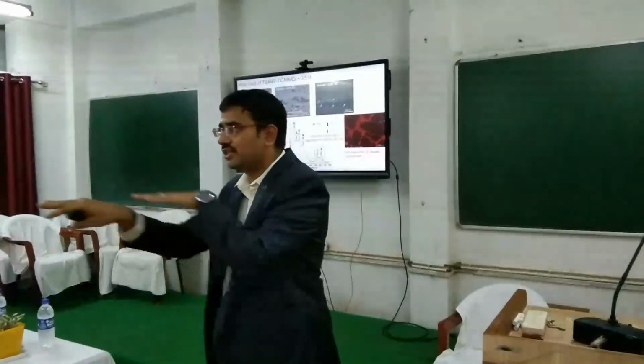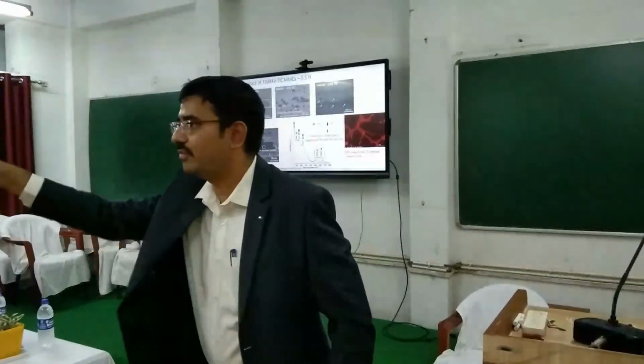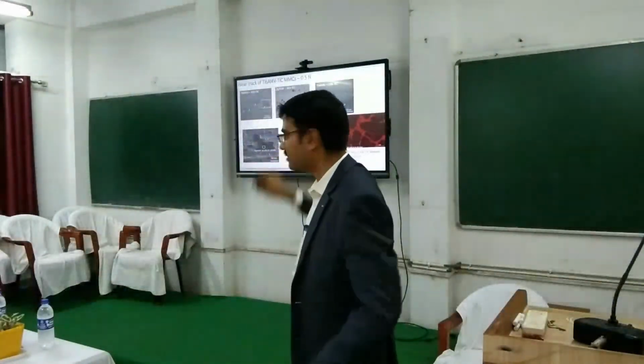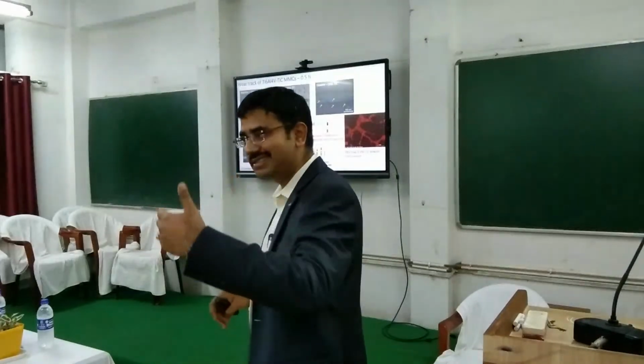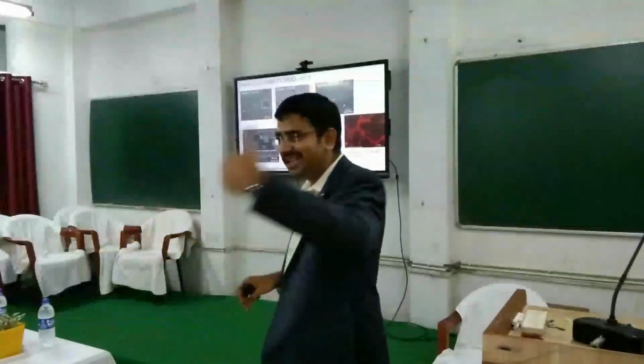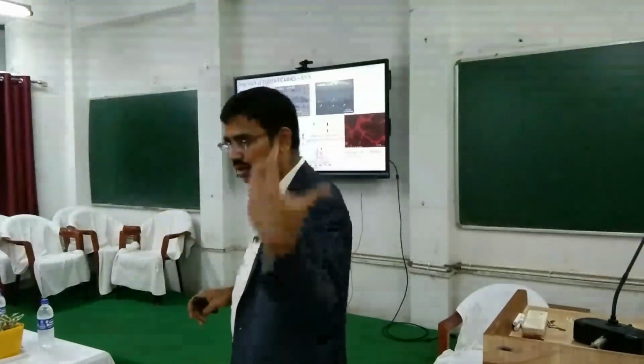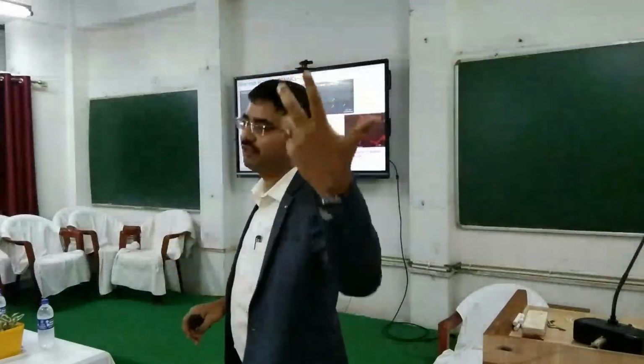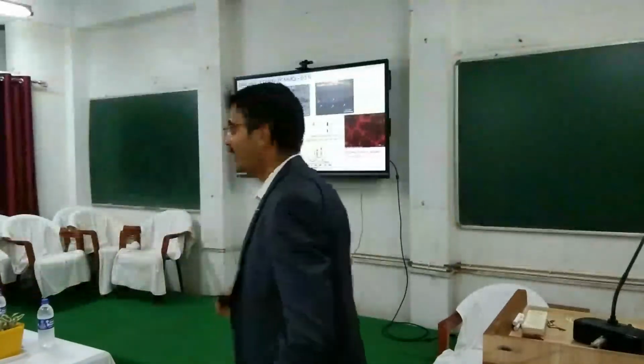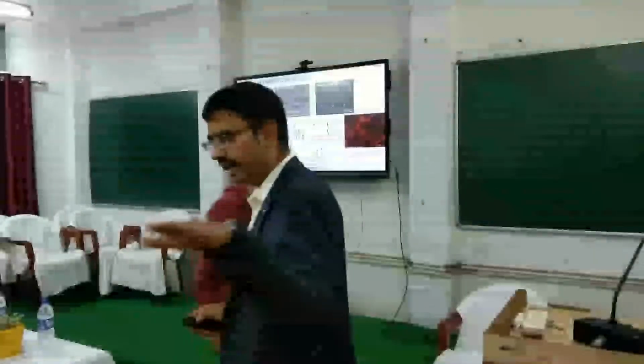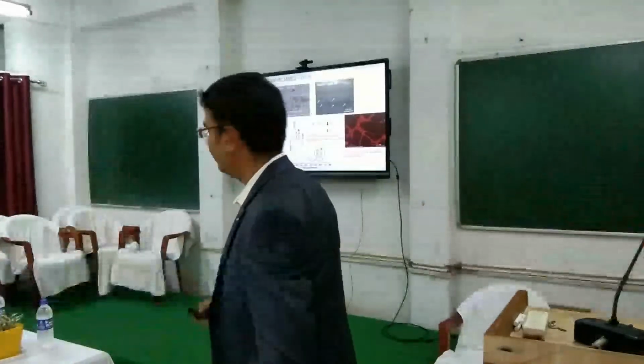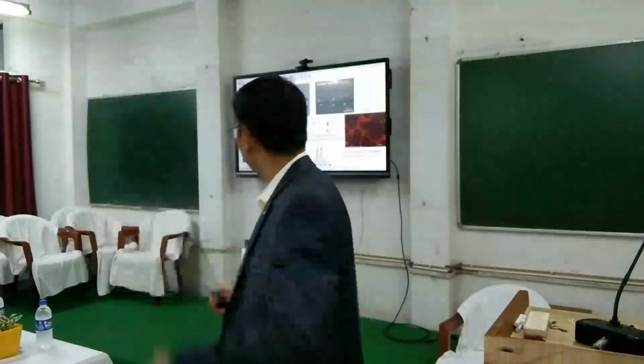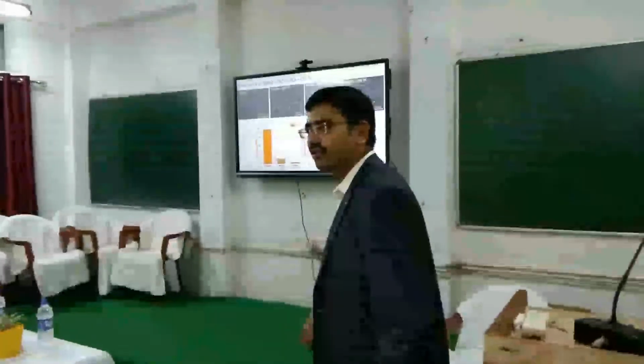So it's giving easy shear. So that's why your friction is actually dropping to 0.3. As soon as these layers form, because these layers are formed during the wear, in the initial cycles where your tribolayers are not getting formed, you see high friction. And once you form these layers, the friction actually drops, and basically they form a layer on top, and that's why you have a smooth layer, and you see a drop in coefficient of friction.